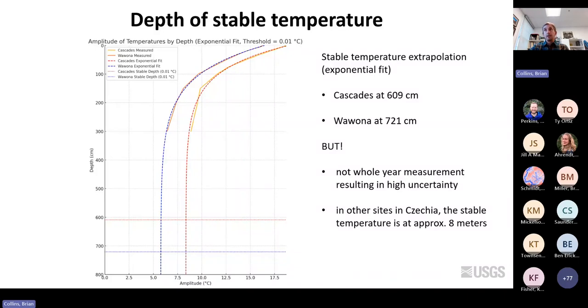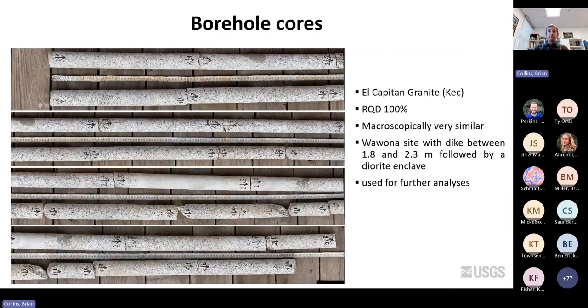So we then looked at the borehole cores we extracted. They are both El Capitan granite. Both boreholes were without any cracks or joints, and the rock cores are macroscopically very similar. Only on the north-facing Wawona side, we have a dike. We drilled a dike between 1.8 and 2.3 meters depth, with a diorite enclave afterwards. And we use these cores for further analysis to compare the properties of these sites.